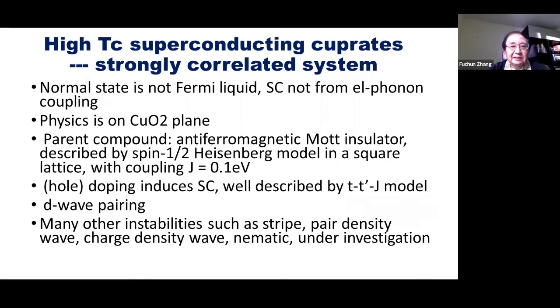However, the high TC superconducting cuprate is very different. That was discovered in 1987. It's a strongly correlated system. And the normal state is not a Fermi liquid. And the superconductivity is not from electron-phonon coupling.